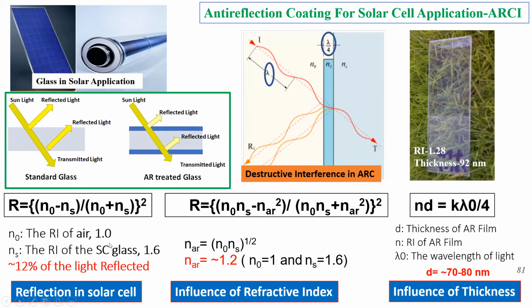So these are some basic equations that we have to use to find out what the thickness of the material should be to make the anti-reflection coating give destructive interference. Based on this, we get a formula: if the refractive index of the material is 1.2, applied on glass having a refractive index of around 1.6, and the thickness of the material is around 70 to 80 nanometers, then overall we can create this property.